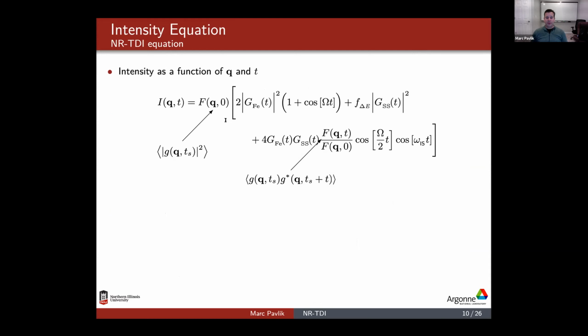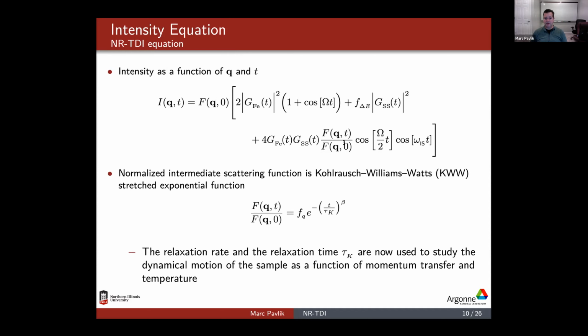The way we want to rewrite this portion of our intensity equation is in terms of the dynamics of the sample. This term comes from the previous slide, and this is the static and dynamic part of the sample. When we write our intensity equation, this is what most people are interested in, because this is the intermediate scattering function, and we use the Kohlrausch-Williams-Watts stretched exponential function as a model to define what's happening to the relaxation time. It's a widely used equation for most disordered systems, and it does a decent job allowing us to measure those relaxation times.